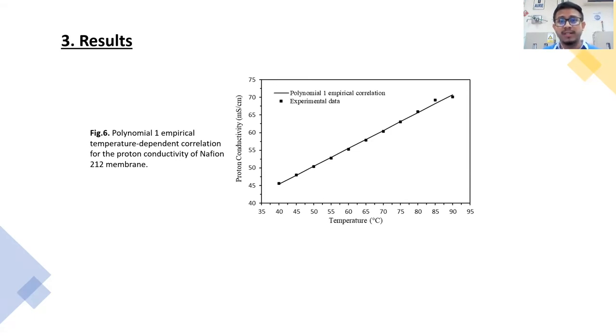Also, for temperatures greater than 80 Celsius degrees, the proton conductivity points are slightly separated from the trend line. This fact can be attributed to the type of the polymeric material. Based on previous studies, it has a maximum working temperature of 80 Celsius degrees. After that point, the proton conductivity can be scattered or decrease in value.